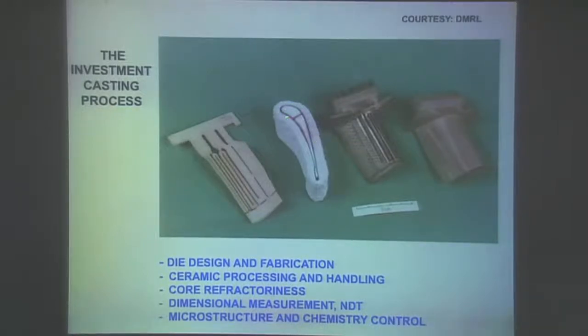That is what the metal is filling. And you can't have the ceramic core touching the ceramic shell during the pouring process. So you actually pin that in place with platinum needles, and you finally get a blade that looks like this after directional solidification, and the half of the blade inside looks like this. And of course, there is the standard metallurgy thing of microstructure and chemistry control in all of this. So, an extraordinarily complex technology for an extraordinary application.